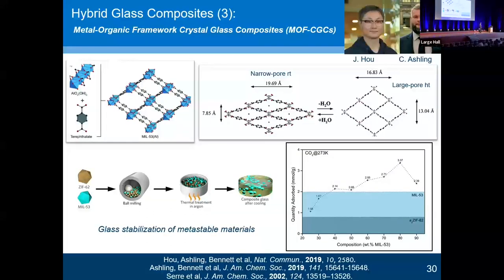Or we can combine a MOF glass with a MOF. These are two hybrid systems which bond well at the interface. And in this case, beautiful work done by Jingwei and Chris Ashling has shown you can take MIL-53, reference to Serre and the late Gerard Férey there, and MIL-53 expands at high temperature and collapses. Trap it within a MOF glass, it remains in its high temperature open state, so you get a better gas absorption from these.